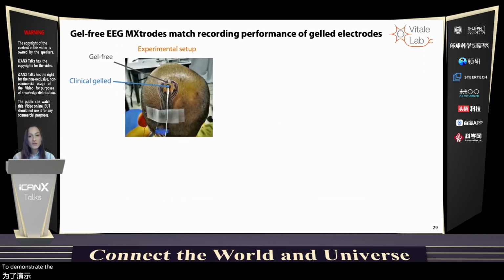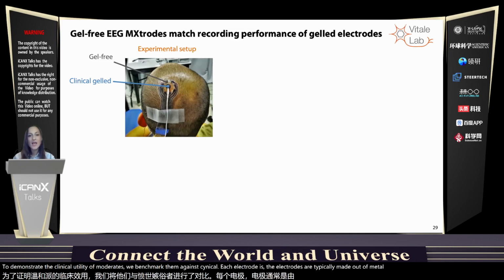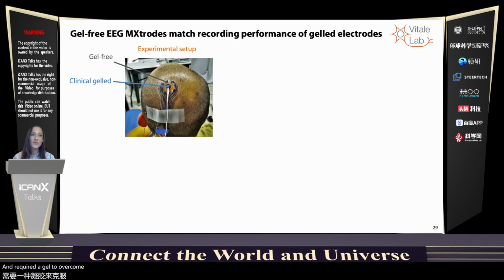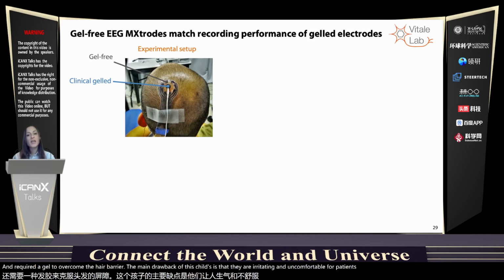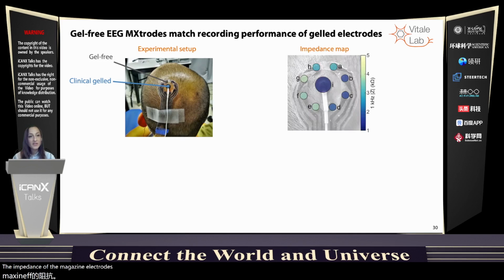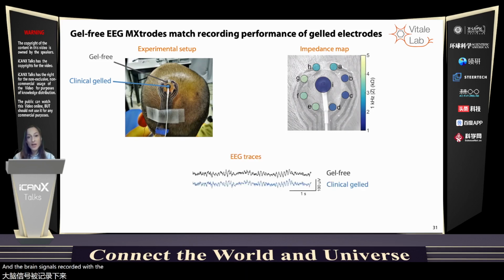To demonstrate the clinical utility of MXtrodes, we benchmarked them against clinical EEG electrodes. These electrodes are typically made out of metals and require a gel to overcome the hair barrier. The main drawback of these gels is that they are irritating and uncomfortable for patients. In this test, we placed the MXene array on the scalp without gel, and then at the center, a clinical electrode with a gel underneath. The impedance of the MXene electrodes and gel electrodes is comparable, which indicates a good contact of the dry MXene electrodes with the scalp. And the brain signal recorded with the two types of electrodes is virtually indistinguishable, not only at the representative location, but actually across the entire array.